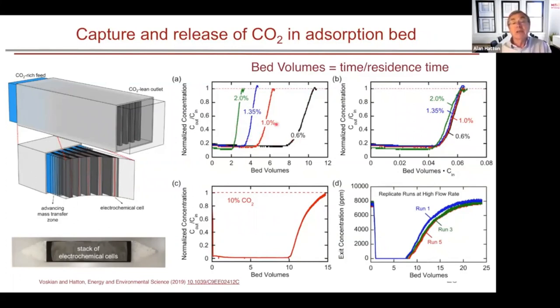And as expected, you'll see for different concentrations of CO2 in the system, we will get different overall residence times required for saturation. And if we look at the normalized, everything falls onto one curve here. And this gives us an indication then of the total bed capacity and how effective these things are in terms of capturing CO2. These are some other examples. This particular case has a residual concentration coming through, which we think was just because of poor hydrodynamics in the system and inefficient packing of the electrodes. We have been able to do it where the actual concentration leaving the bed is essentially zero for a large number of bed volumes before we get breakthrough in the system.